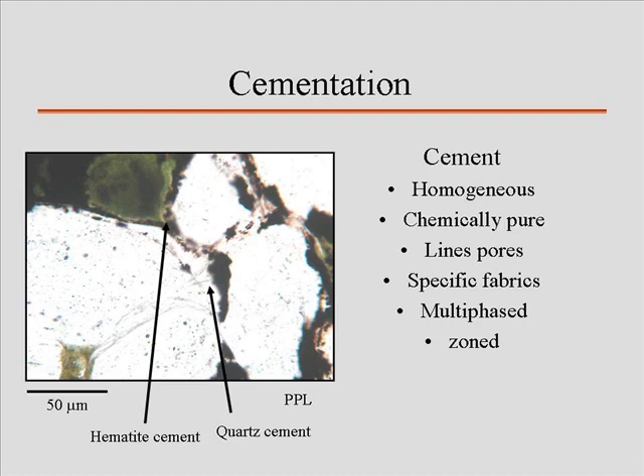But what you're looking at here is a sandstone with at least 3 phases of cements that are identified. There's a quartz grain in plain polarized light. You can see the dark stuff that clearly is filling the void spaces. There's actually 2 colors here. There's a little bit of green, that's glauconite, and this stuff has a brownish color to it. That's hematite. But even before that, there is a thin layer of quartz cement. 3 phases of cements. This is what we're talking about, multi-phased pore filling.